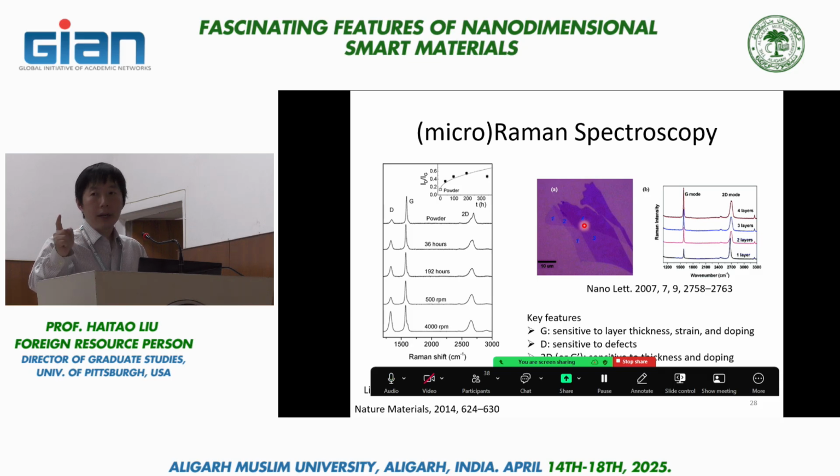Now, if you deposit graphene onto another substrate, you may not be so lucky. For example, a graphene sample supported on a copper substrate. In that case, you don't have this optical cavity. In those cases, you have to integrate your signal for like an hour before you get any meaningful signal. And oftentimes, an hour is not enough.